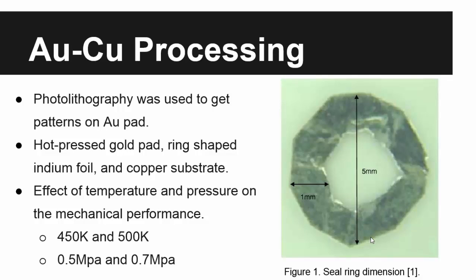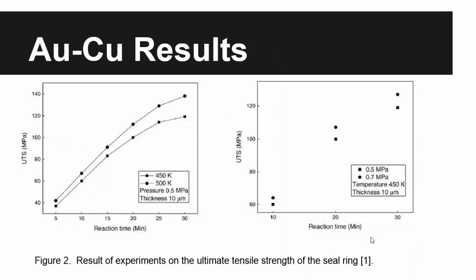So I'll discuss the processing of gold and copper. First, photolithography was used to get the pattern on the gold part, and then the gold part is hot pressed with ring-shaped indium foil and copper substrate to form a seal ring like the pictures shown on the right side. And the effect of temperature and pressure on the mechanical performance was investigated at 450 and 500 K temperatures and at 0.5 and 0.7 megapascal. And here are the results. The pictures show that higher temperature and pressure result in a stronger ring seal.